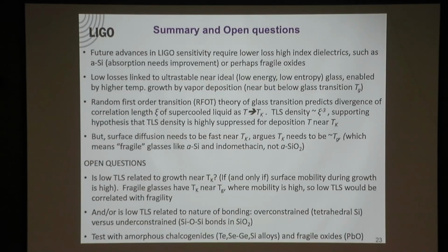But I will leave you with the summary. The summary of all this: future advances require lower loss, high index dielectrics, maybe amorphous silicon or maybe some fragile oxide. We believe there's a correlation with what's called the fragility. The low losses are linked to this ultra-stable, near-ideal, low-energy, low-entropy glass, which is enabled by high temperature growth of vapor deposition.